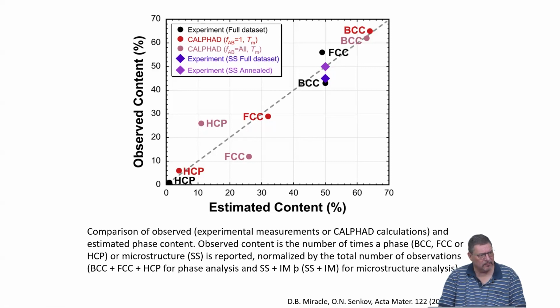And basically that is meaning the fraction of data sets which have been assessed of the binary A-B systems which make up your 5-component system. So if all the 5 binaries have been really thermodynamically assessed, meaning completely calculated by Calphad and confirmed that reality is the same as the Calphad calculation, then the FAB would be equal to 1. So the fraction is 1 means all of them have been assessed. And if you take also smaller numbers, like maybe out of the so many binaries, only half of them have been assessed, then the FAB would be 0.5.